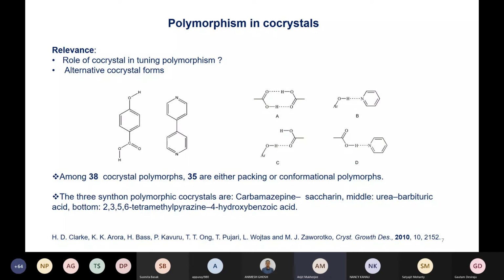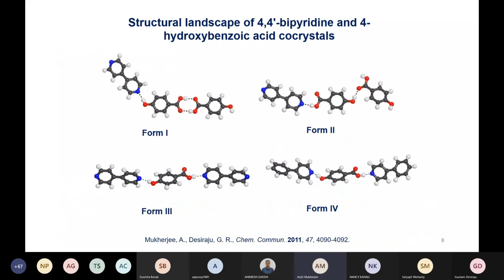When co-crystals are formed, they are formed through synthons. And a study by Professor Zaworotko's group in 2010 showed that among 38 co-crystal polymorphs, 35 are either packing or conformational polymorphs. That means the propensity of the formation of these synthon polymorphs is very rare. And we tried to investigate why it is so. So we had taken this hydroxybenzoic acid and bipyridine system. We obtained 4 forms: form 1, form 2, form 3, and form 4.